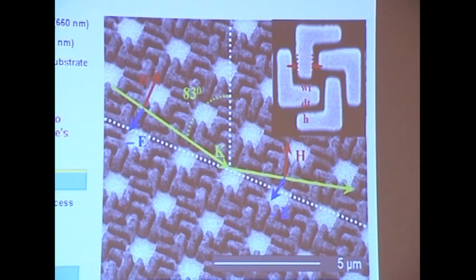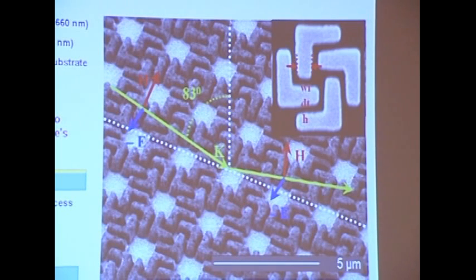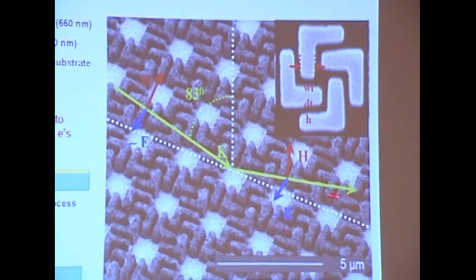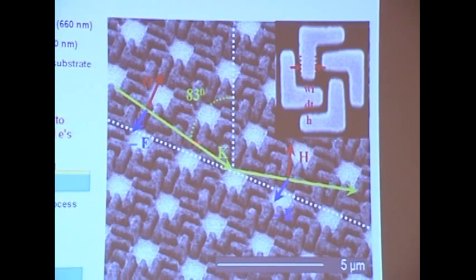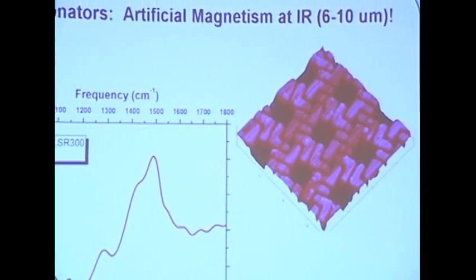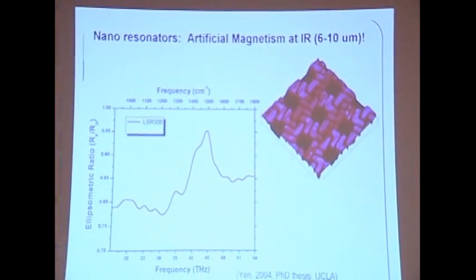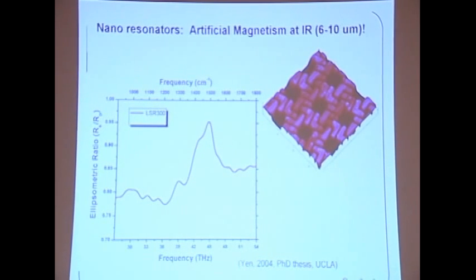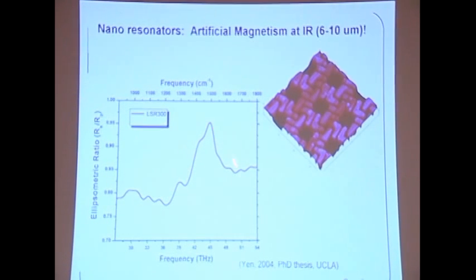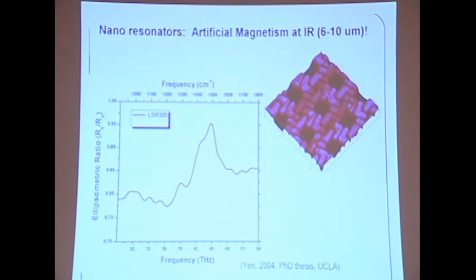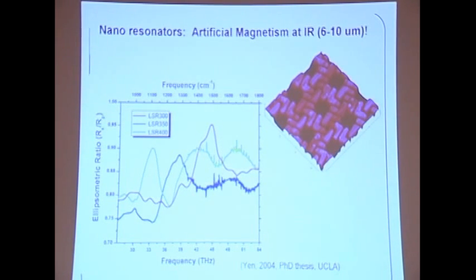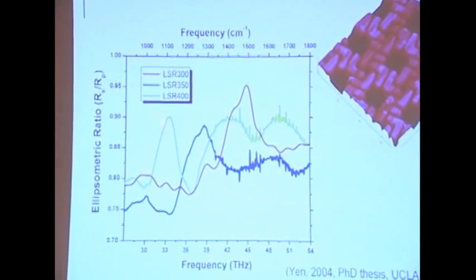By structuring smaller, you push up the frequency. So this is designed for the middle infrared. The measurement is very similar. You have an incident beam coming in, and you measure its ellipsometry response, and you have a magnetic component almost perpendicular to the ring, such that it generates the resonance through the inductance-capacitance coupling. Here is the brief result of what we believe is the first response at 6 micron middle infrared. You can see quite a pronounced response of this magnetic structure. And of course, by changing the size of the geometry, you can tune the response from 6 micron all the way to 10 micron in this case.